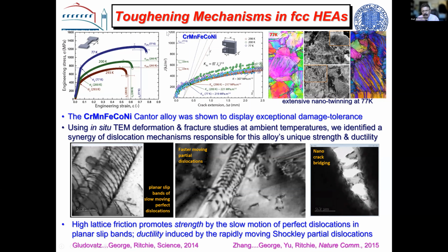Now, we measured the toughness of these. This is the fracture toughness. And we found that the toughnesses, these are R curves again, they're done in the J integral, but the fracture toughness was above 200 megapascal root meters. Now, this is a material with a pretty high yield strength, tensile strength, about 1.2 gigapascals. So this represented a very interesting type of material, that it combines strength and ductility again, which gives it its high toughness. Generally, when you go to lower temperatures, the high strength means your toughness erodes, but this one,